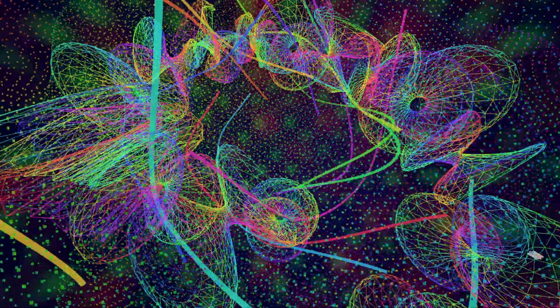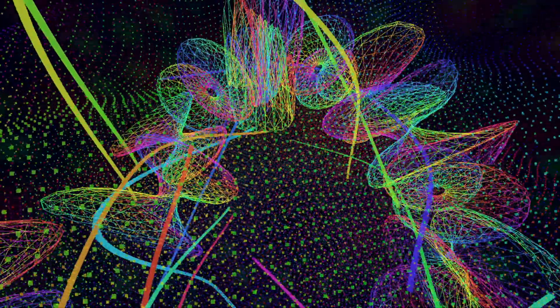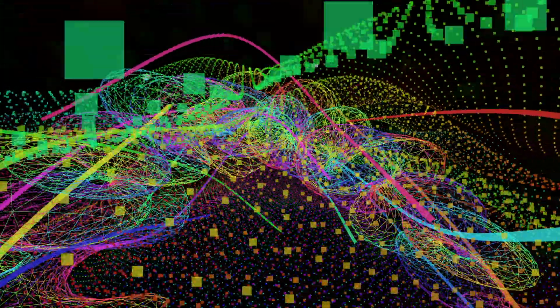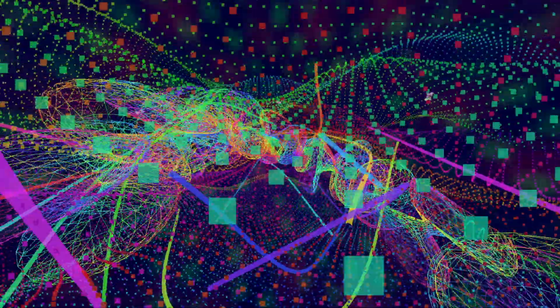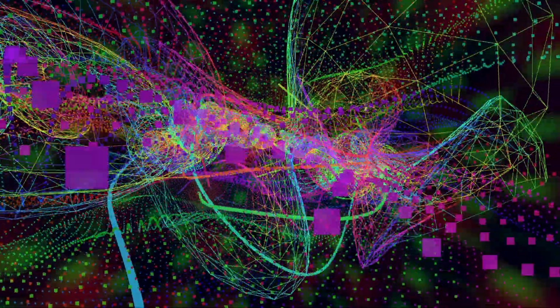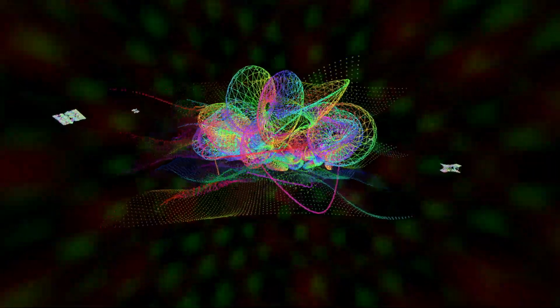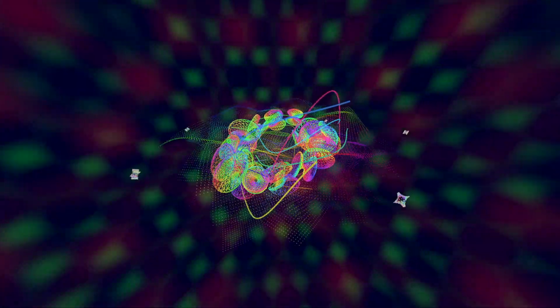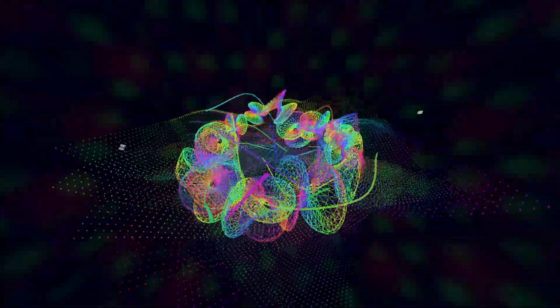Okay, so what happens to the light that doesn't have that energy or has too much? Good question. That's where the waste comes in, as the sources detail. First, you have the sub-bandgap photons. These are mostly the infrared photons. They just don't have enough energy individually to knock an electron across that 1.12 eV gap in silicon. Too weak. So they basically either pass right through the silicon untouched, or maybe they get absorbed but just turned into a tiny bit of heat. Useless for electricity. For silicon, that's light with wavelengths longer than about 1,100 nanometers. A significant chunk of sunlight, right? A very significant chunk, yes.